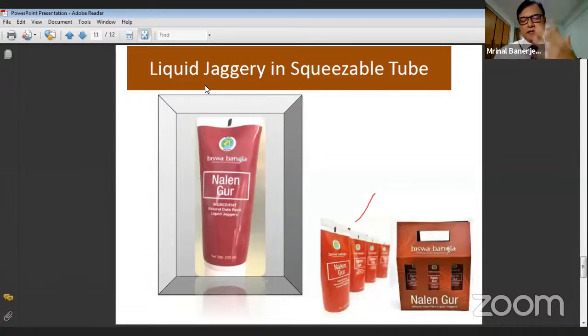But then the government did excellent work with the cooperative and their association. So they collect it, and with a flat pan they slow heat it, evaporate it, and when the jaggery formation happens, they pack in hot conditions, anything between 60-70 degrees. And it remains. Actually, it remains for 2 years, not 6 months.